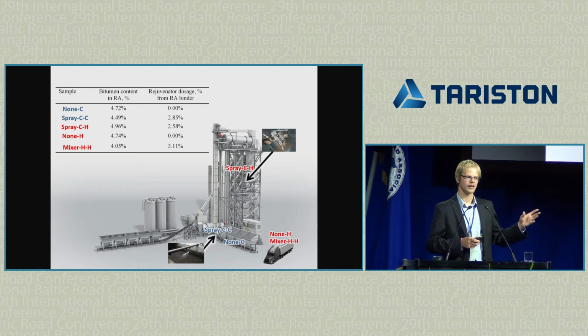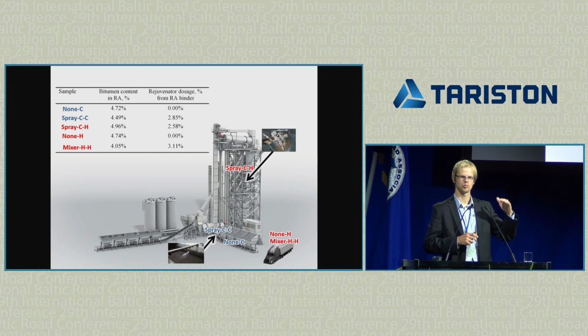So now I have my 5 different addition spots, and I wanted to have 3% of rejuvenator dosage at each of these spots. Unfortunately, since this is a real production process, the reclaimed asphalt binder content varied. So although my dosing was the same for each of these cases, since the reclaimed asphalt binder content varied, obviously my proportion of the rejuvenator also varied a little bit. So instead of 3%, I got somewhere between 2.6 and 3.1.